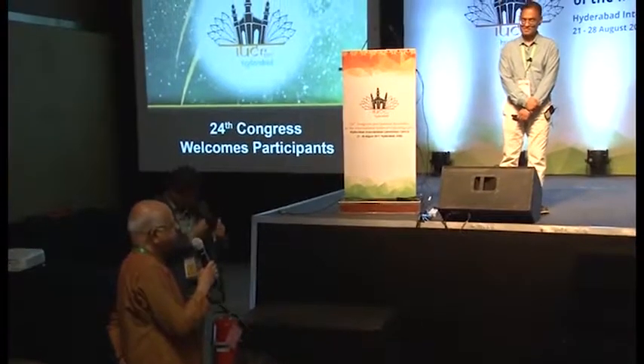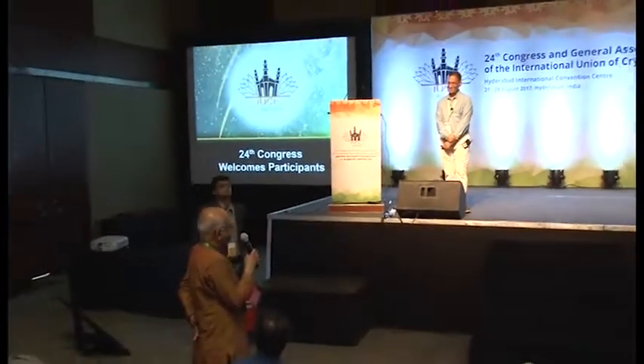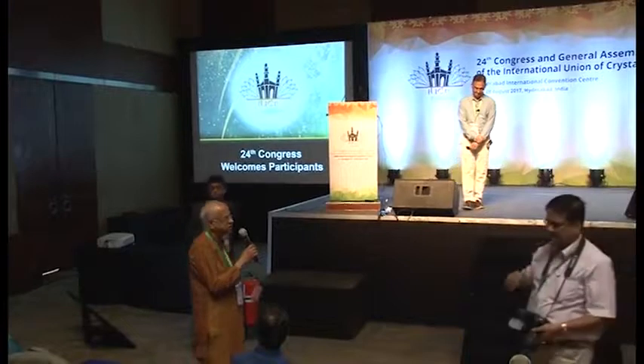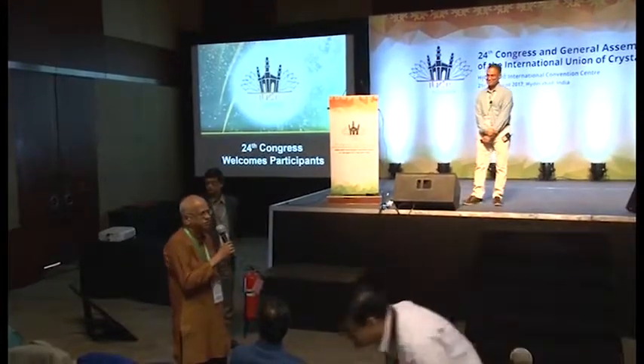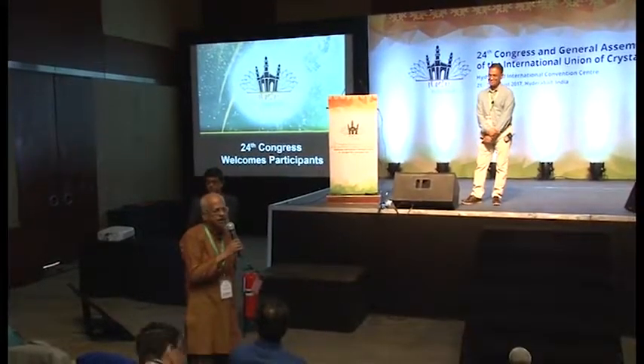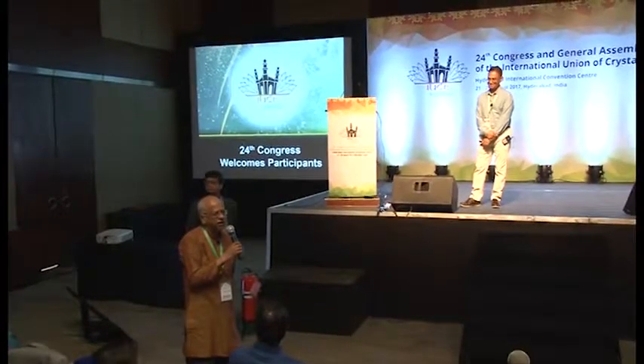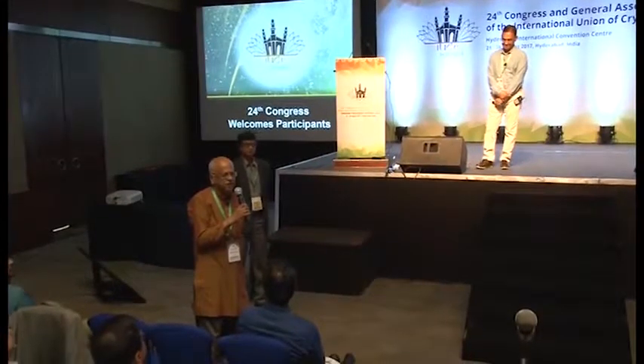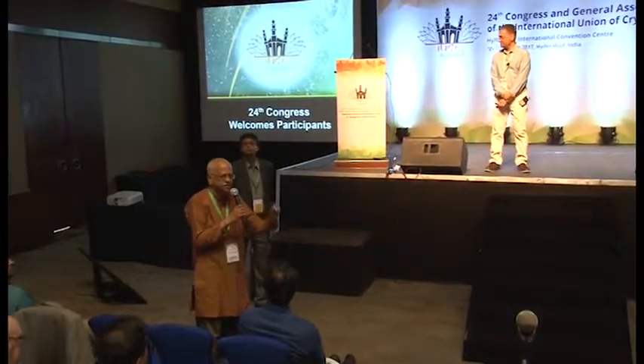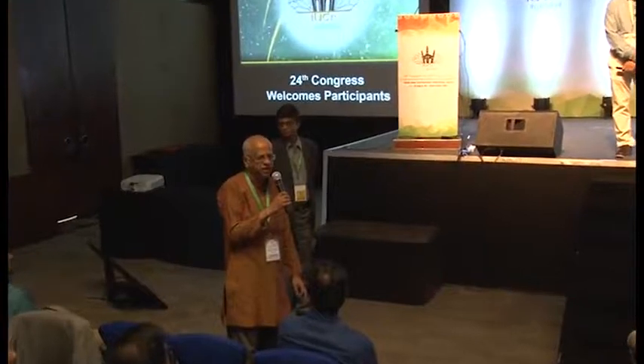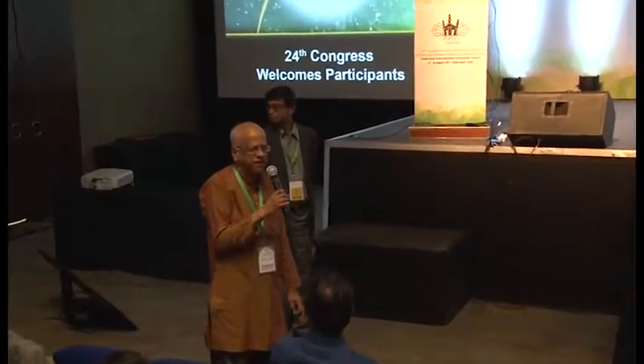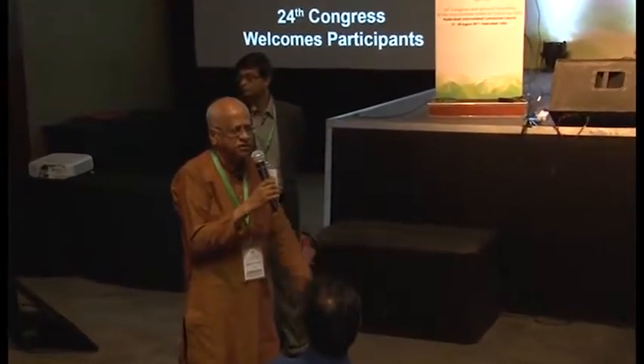Also a message to young PhD students in the audience. It's very nice to have a PhD problem where you don't get to the answer in the end and it remains unsolved. And I don't believe the problem of phenyl quinhydrone has still been satisfactorily resolved. There are two domains of P21/c and P21, and the X-ray result just shows P21/c. It showed a SHG very clear, and of course that shows that there are P21 domains.